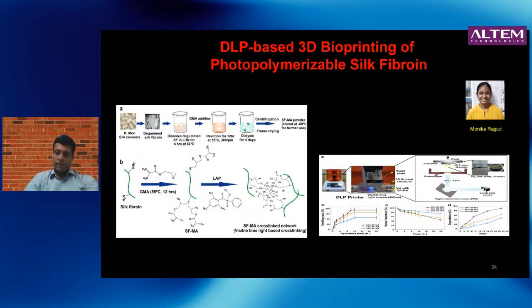So we use this Lumen X printer for our work, where we have a vat where we take this acrylated silk, we dissolve it in an aqueous buffer or in media, and then we have a photo initiator in it, and then you shine the light right at the plane in which there is a stage, so that the polymer gets cured there and it gets stuck to the stage. And then you lift the stage up a little bit, and again the next layer of pre-polymer is cross-linked. The cells are suspended in the solution itself. So as we build this up layer by layer, we are able to build up a scaffold of interest.